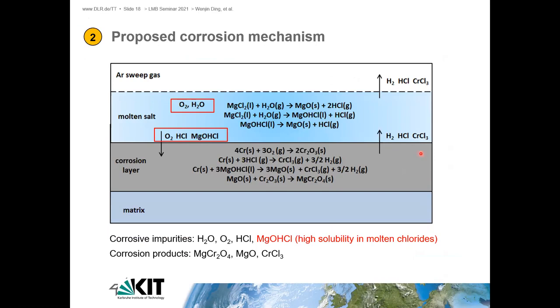We proposed the corrosion mechanism is that the main impurities come from the atmosphere or from the adsorbed water or hydrolysis of the water in the salt, and during the heating, the MgOHCl will be produced. It is stable in the molten salt and can dissolve in the molten salt. Then it can corrode the alloys at high temperatures.